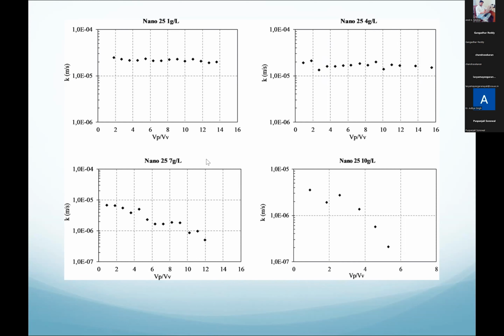They also provide particles in a dry form, and they tell you how to mix it to make a suspension. So basically, we got these commercial nano iron particles from Czechoslovakia, and then we tested them at different concentrations: 1 gram per liter, 4 grams per liter, 7 grams per liter, and 10 grams per liter.